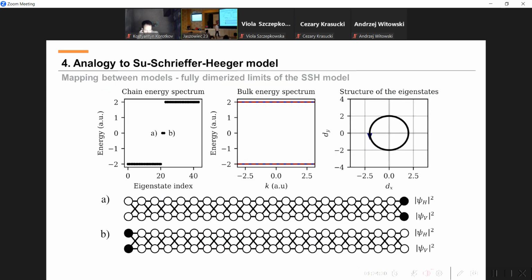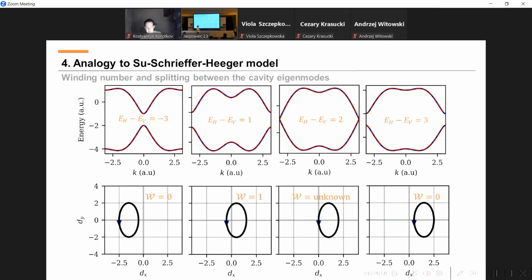Here we assume that we have a dimerized model, but in the other case, when we are beyond this SSH model, we have also this topological state, and this state can be tuned just by splitting between horizontal and vertical mode. In that case, probably we can obtain real experimental parameters to change this topological phase from the trivial phase to the topological phase, just by keeping different values of the splitting. Thank you.